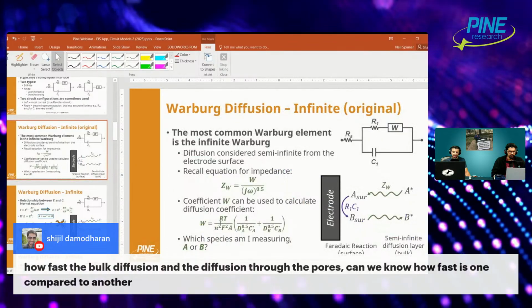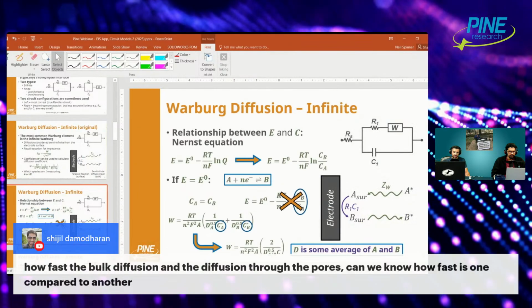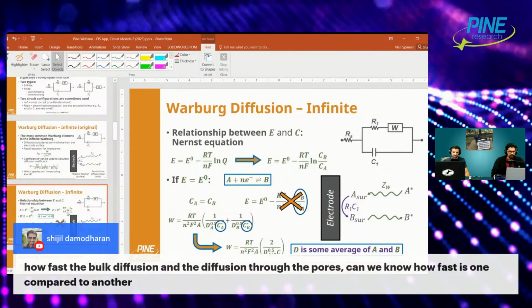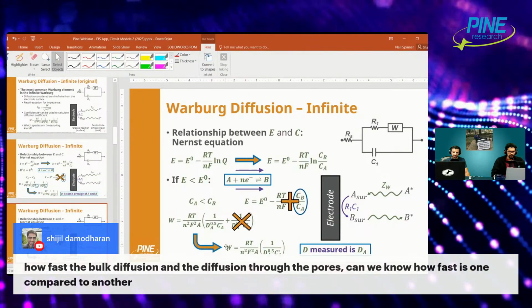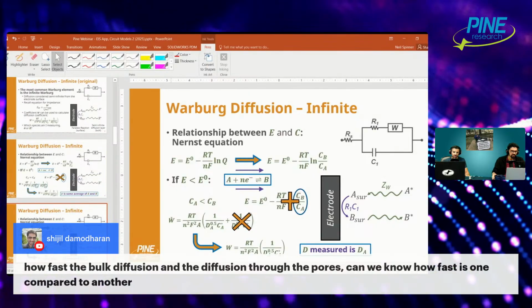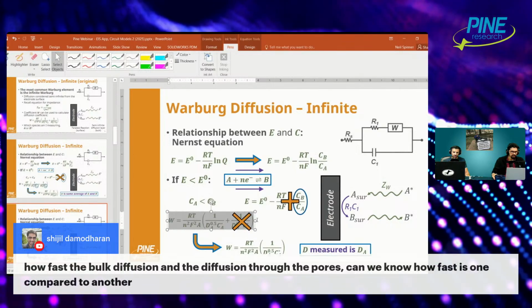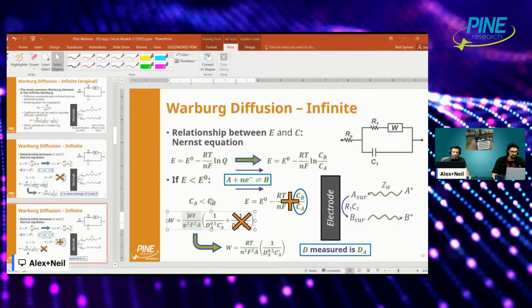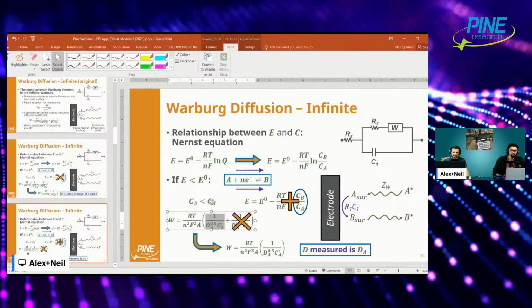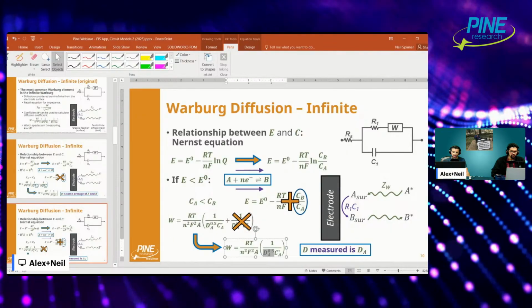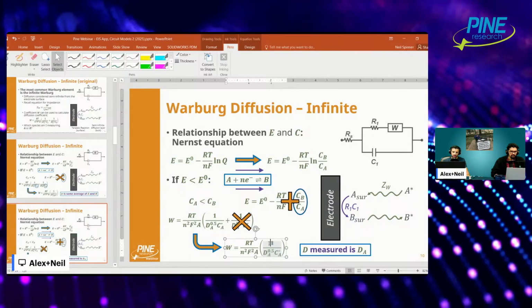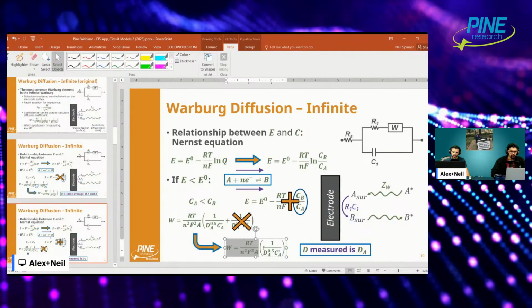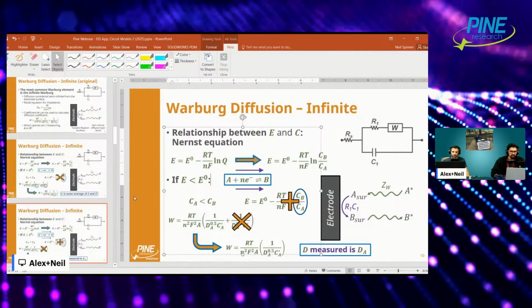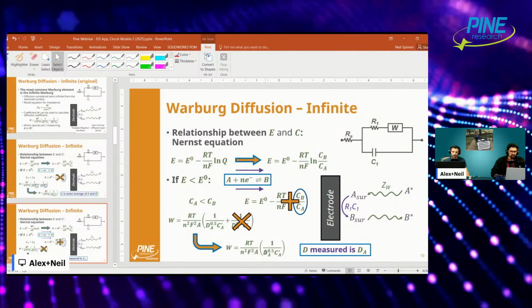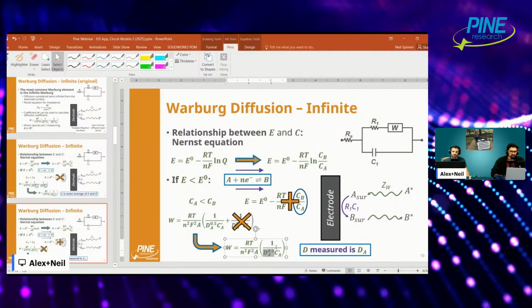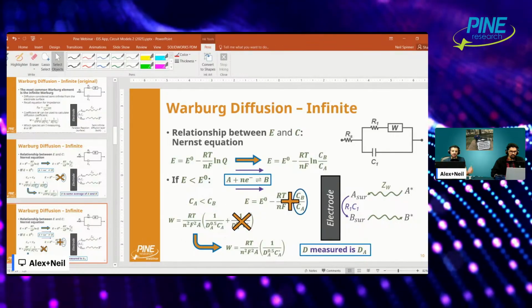And then calculating the diffusion coefficient, there's a bit of a walkthrough here, but loosely speaking, it's something like this. You're using this expression where the Warburg impedance is equivalent to RT over n squared F squared A, and then you have the diffusion coefficient and the concentration of the species in the bulk. This is for the most simple case, from Bard and Faulkner. Typically, you can extract the diffusion coefficient from this expression if you know the Warburg constant from your fitting.